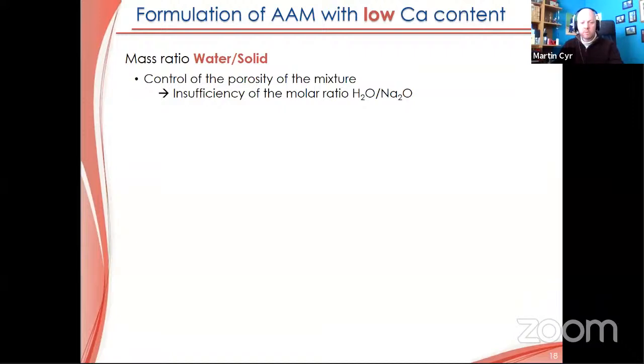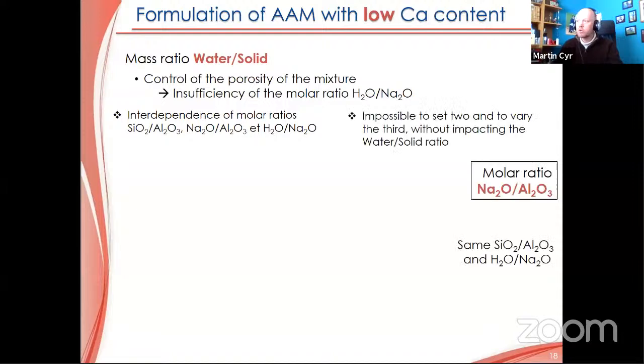What about now the water-solid ratio? That's something very important for the Portland cement. And sometimes we see a molar ratio, water over sodium. Is it efficient enough to control the material? In my sense, probably not, because there is a strong interdependency of the molar ratios between them. That's the kind of molar ratio we can see in the literature. And it is very difficult to set two of these molar ratios without impacting the water-solid ratio inside.